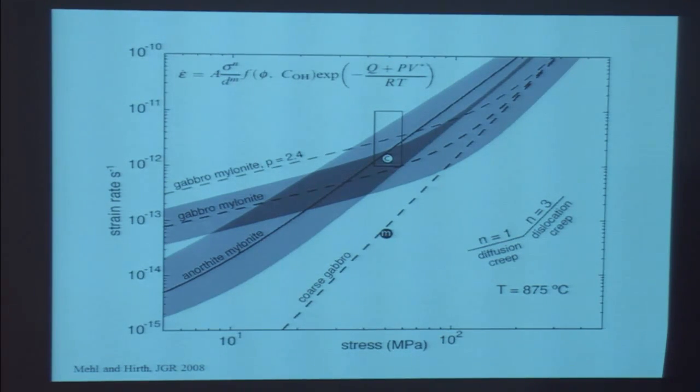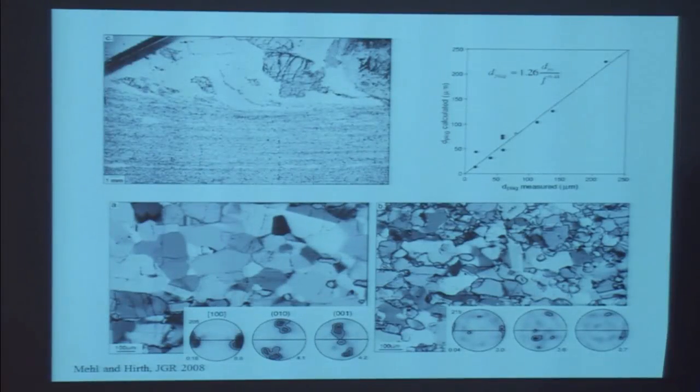And just to demonstrate that, if the stress was larger, there's one other thing that's important, is that the fine-grained rock, the strain is localized into the fine-grained rock. Let me quickly, in the last minute, just show you that. It's pretty remarkable, right? So here's just a few millimeters away. This is 1 millimeter. The sample is not really deformed very much. But in the fine-grained rock, the strain rate is way higher.